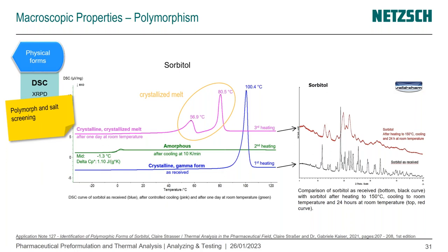For polymorph, one of the tests that has to be done is taking this drug material and solubilizing it in different solvents, for example, at different speeds, changing the conditions in which the crystals are formed, and then checking if we have polymorphs. It has to be tested, and this is called polymorph screening.